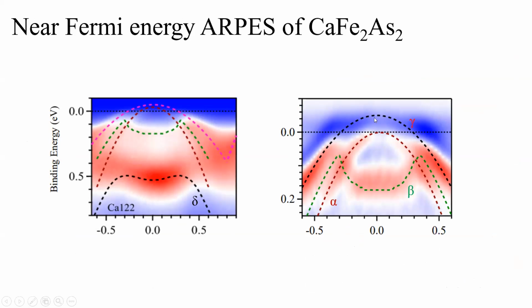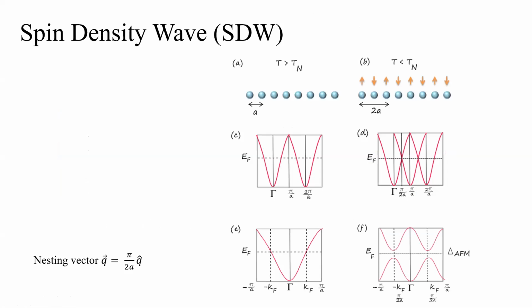Actually, this band is also expected to cross the Fermi energy, but because of the SDW phase ordering, it shows a back band folding, which I can discuss here. If the temperature is above this TN value, TN being the antiferromagnetic ordering temperature, then you have this vector of a, the translation or lattice vector, and because of that you get a band using the tight binding model. Now if there is a transition, we have a spin up here, a spin down here, a spin up here, so the lattice vector is now twice the initial one. The Brillouin zone becomes smaller than in the earlier case, and because of the lowered symmetry these bands which were here have now moved to this position also.